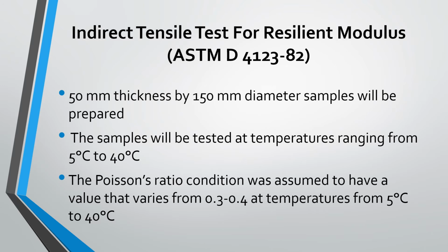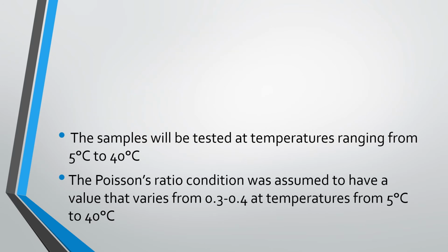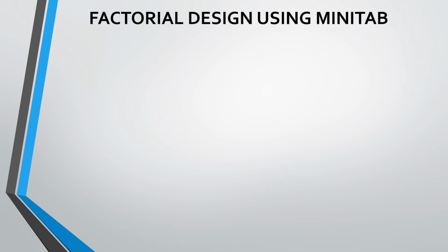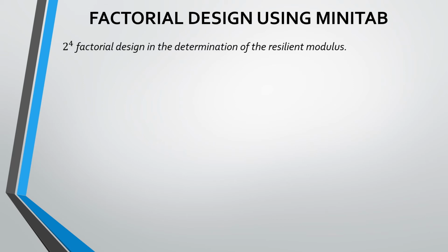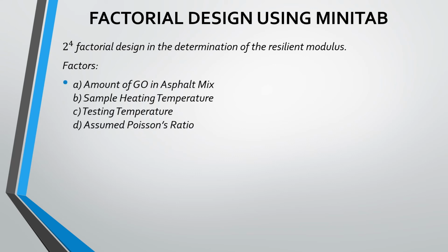Again, in order for us to have a simpler experimentation, we will consider a factorial design of experiment. Specifically, a 2 to the 4 factorial will be used in the determination of the resilient modulus. The 4 factors that we need to consider are the amount of GO in asphalt mix, sample heating temperature, the testing temperature, and the assumed Poisson's ratio. We will have 2 levels for each factor.